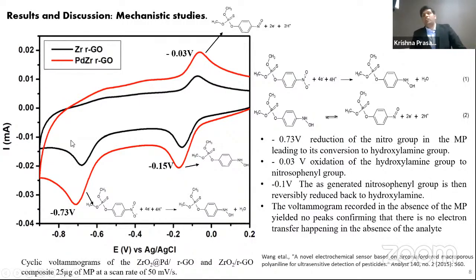Also, it is important for us to know the reaction mechanism so that we could predict how the interference mechanism could occur. So when we studied the reaction mechanism, we found that initially in the first cycle there is no peak at minus 0.15 volts. The first cycle gives a peak at minus 0.7 volts, which is the reduction of the nitro group to the hydroxylamine group. And subsequently, in the oxidation process at minus 0.03 volts, the hydroxylamine group is converted to the nitroso-phenyl moiety, and then in the ensuing cathodic sweep, that nitroso-phenyl moiety is reversibly reduced back to the hydroxylamine. This is the reaction mechanism, and the reactions have been summarized in these two equations for you all.